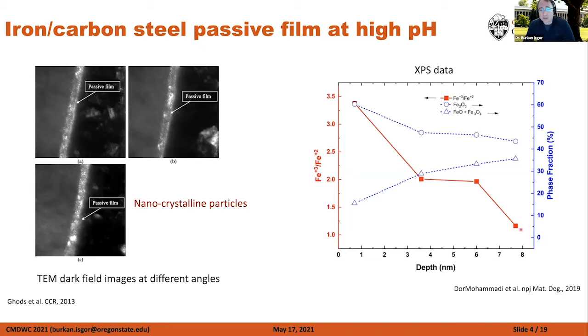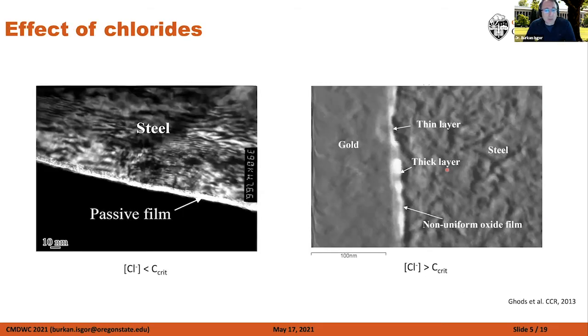So there's a bilayered structure, and as you get closer to the outside surface, the Fe3 percentage increases. So the outer side of the passive film seems to be more rich in Fe3 oxide, and the inner side of the passive film is more rich in Fe2 oxides. And other people have shown this as well, so this is not necessarily new information.